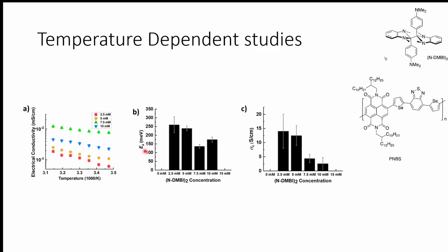Normally, if it's around 25 millielectron volts, that's room temperature, so it's negligible. But here it's like 10 times that. So that's a major contributing factor for our polymer film to not be conductive. This is the other facet of doing these experiments: when you get something that's not conductive, or that's giving you disappointing values, you try to rationalize why this is happening. So you start with a pretty high activation energy barrier that can go up to 300 millielectron volts.